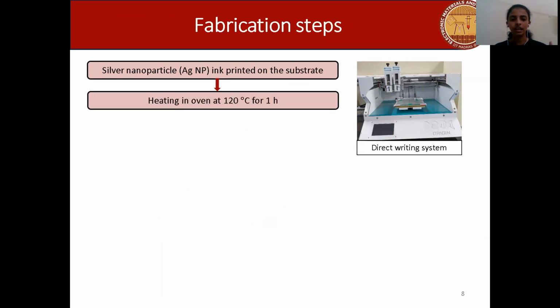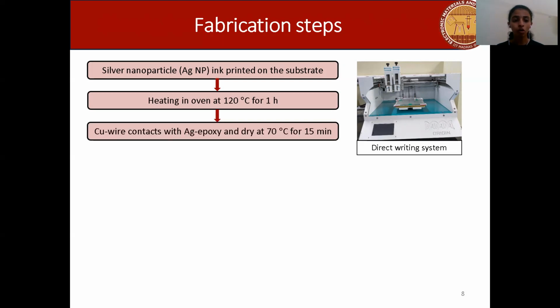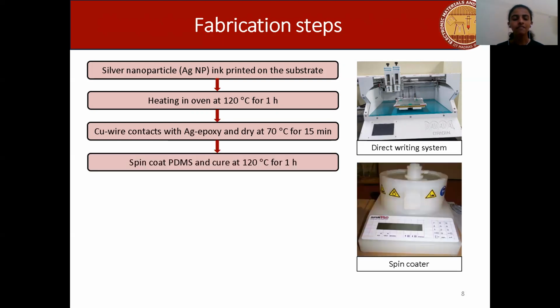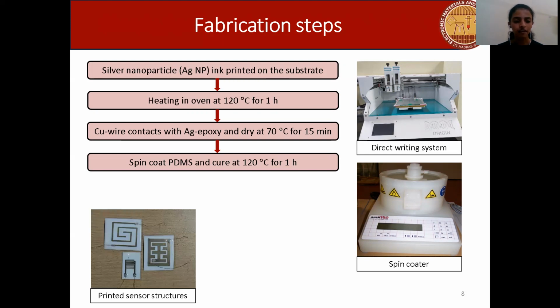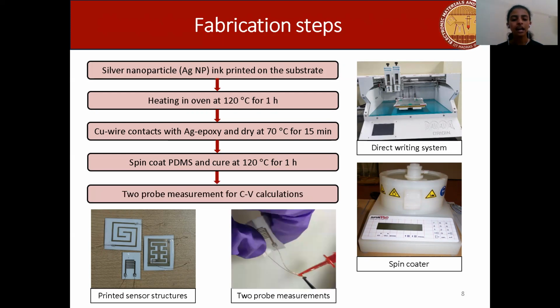After heating it in an oven at 120 degrees centigrade, I've made copper wire contacts using silver epoxy. After that, I've spin coated PDMS on top of the structure and cured it at 120 degrees centigrade for 1 hour. These are the 3 structures that I've printed using the direct writing system. And after that, I've done 2 probe CV measurements to observe how the capacitance is varying with voltage in both plane and bent conditions.